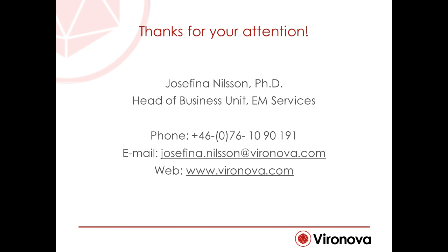And can you measure PEG layers of liposomes using any of your electron microscopy techniques? So we cannot see the PEG layer because it is not dense enough to be seen by electron microscopy. The PEG layer is composed mainly or exclusively of oxygen, hydrogen, and carbon, and this doesn't give enough contrast with respect to the support. The support is made of carbon, and the PEG molecules are also made mainly of carbon, which doesn't provide enough contrast, and unfortunately, no, this is something that we cannot provide you.